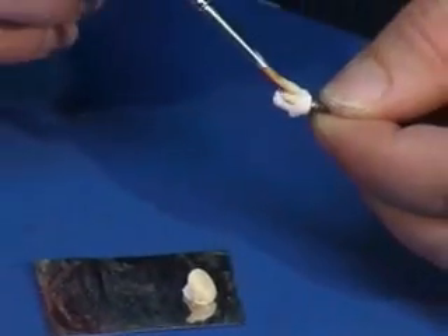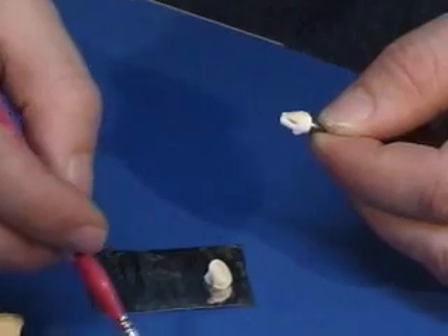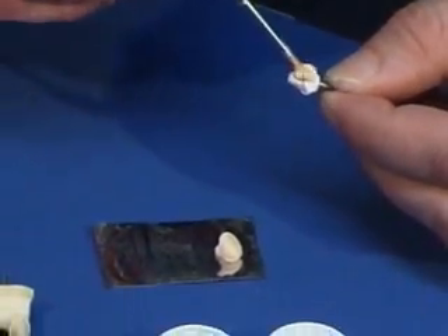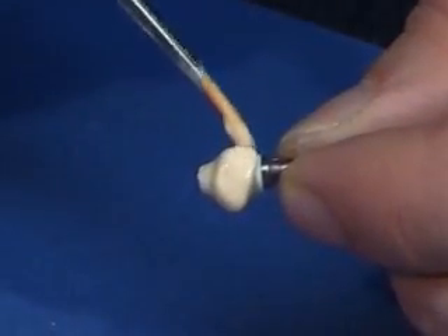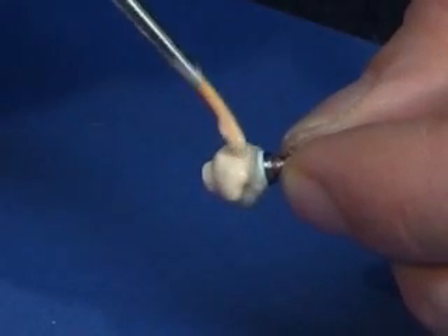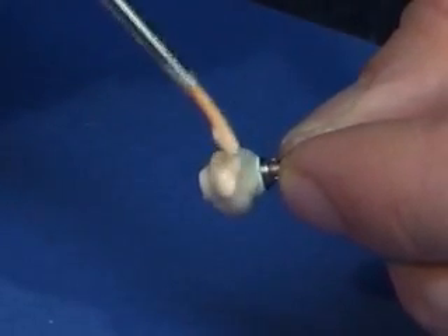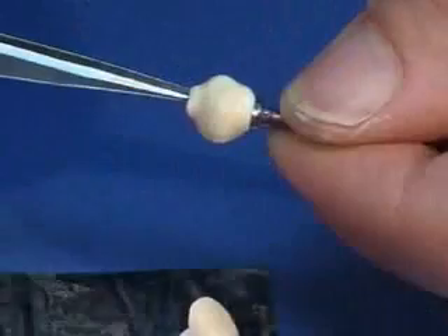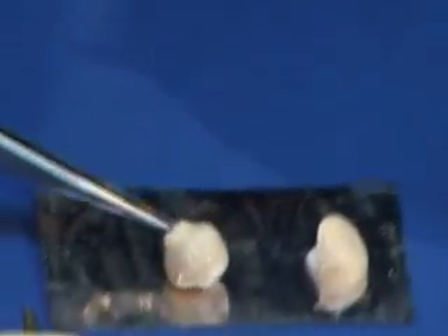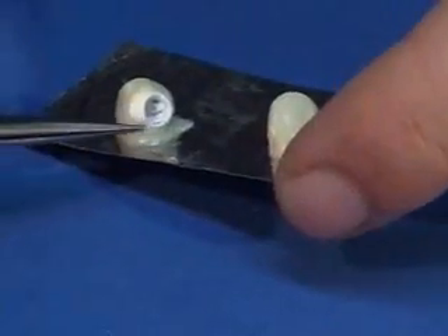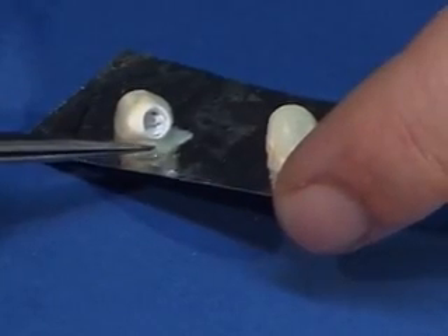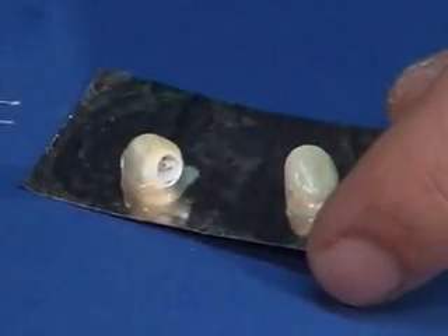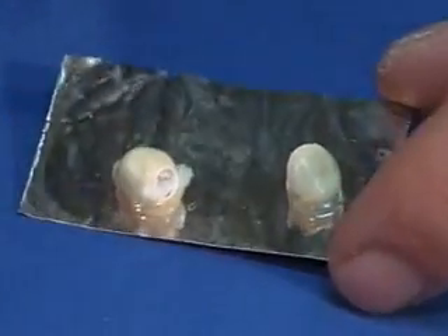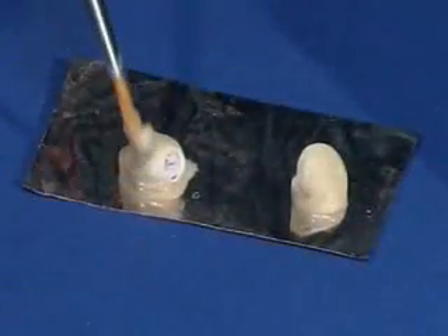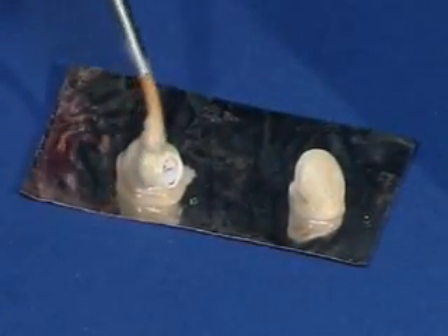Glass infiltration is performed in the same way as you did with single copings and bridges, except for a few points, namely the thickness of the applied glass has to be much bigger to maintain complete infiltration of the thick abutment walls. Provide a horizontal position of the abutment on the platinum foil to prevent the glass excesses from flowing inside the abutment. If they do, after the bake, you lose too much time removing them by sandblasting. When the framework is already on the foil, apply some more glass.